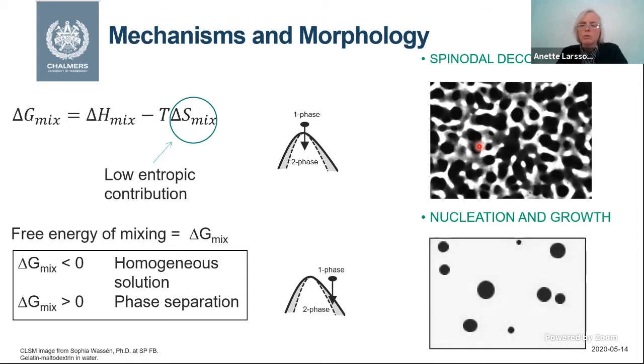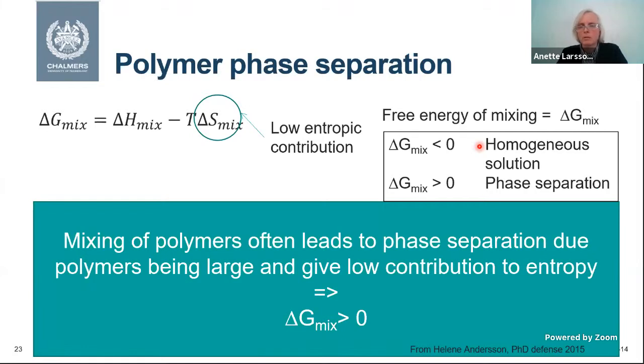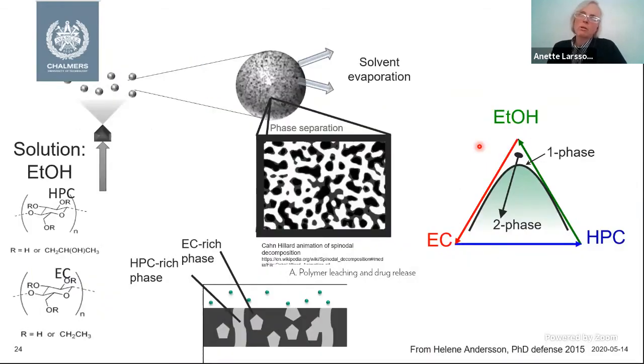And we could show that depending on, this is just to say that the entropy contribution for polymers is low. So we could show that depending on the molecular weight, the phase diagram was changed. So we could get both spinodal decomposition and nucleation and growth, which had a lot of impact on the controlled release. Because if you have